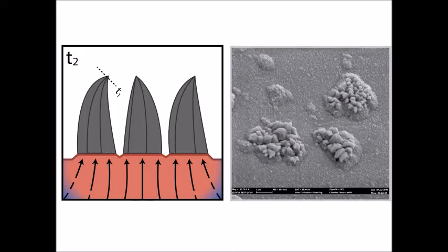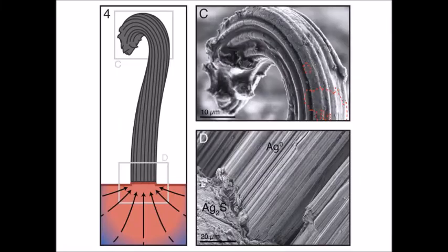Now we can see in the SEM image that when the acanthite, which is the background material here, turns to argentite, there's a slight increase in the volume, and you can see that by the formation of these pedestals. And then forming on top of the pedestals are the initial sprouts of wire silver. Now, individual sprouts will start to grow and then coalesce and eventually become a large wire like the one that we see here in the schematic and the image that we see on the upper right.